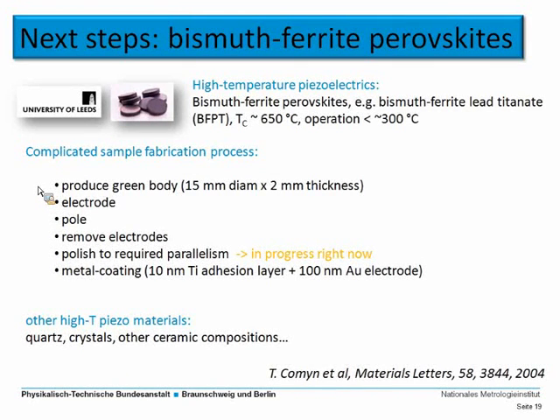We saw that the poling induced some dramatic change in the surface shape. So after poling, we have to remove the electrodes again, have the samples polished to the required parallelism, and then metal coat them again with our very well-defined electrodes that we need in the measurement. And this polishing is in progress right now, so we're just waiting for the first batch of samples to come back to us, and then once they are finished, we can do measurements on them. So if you want to know how this continues, just keep in touch.